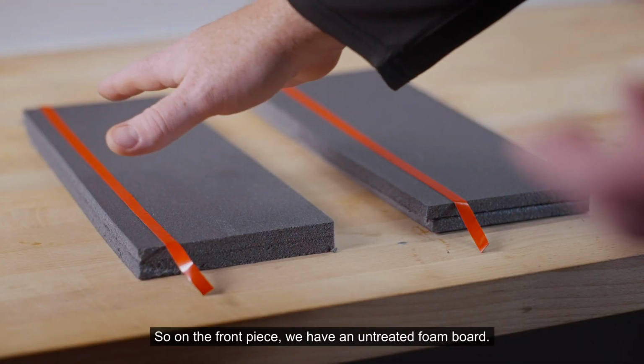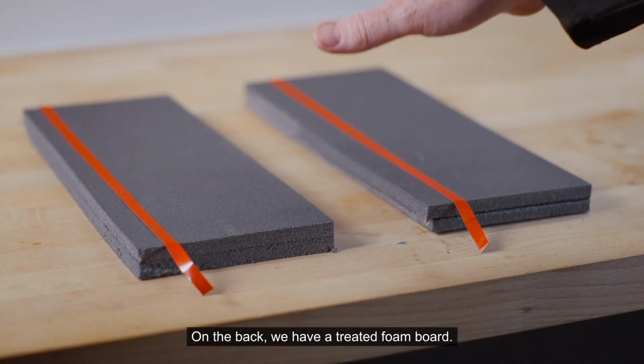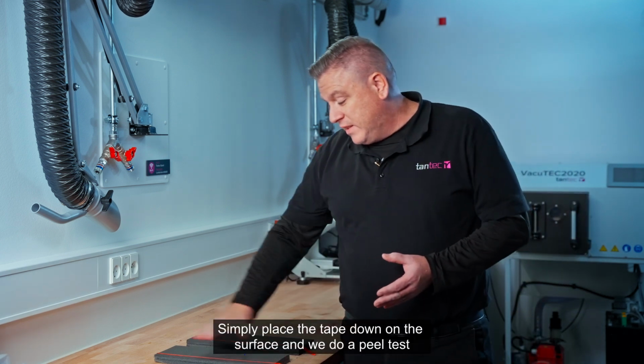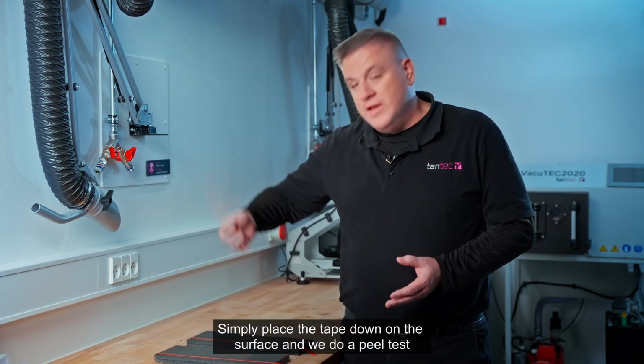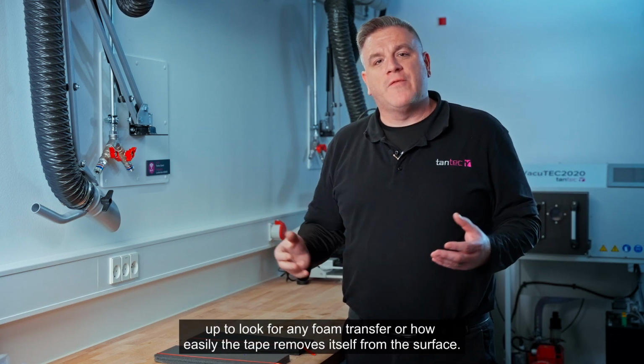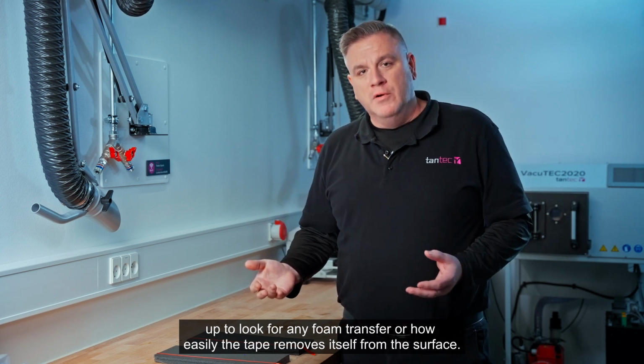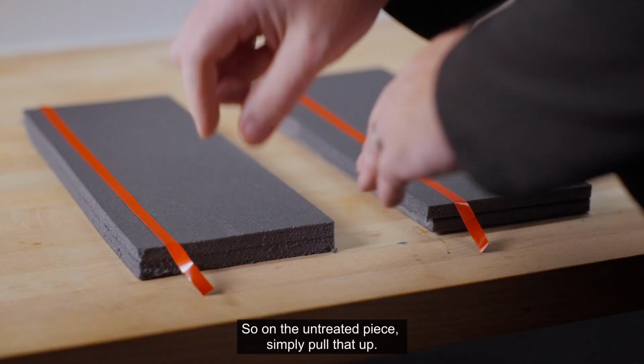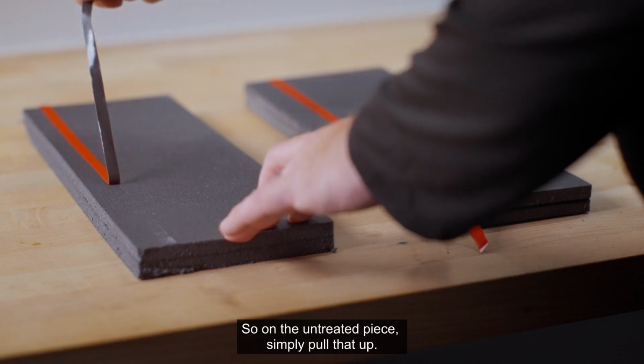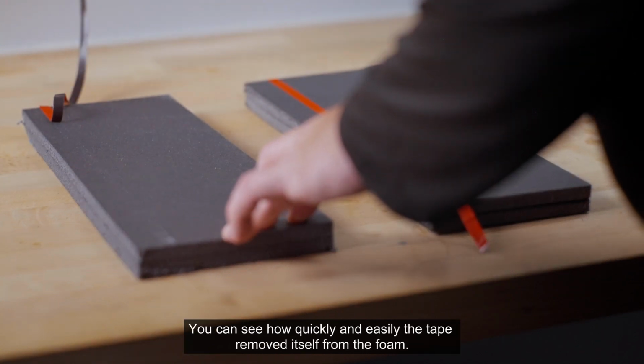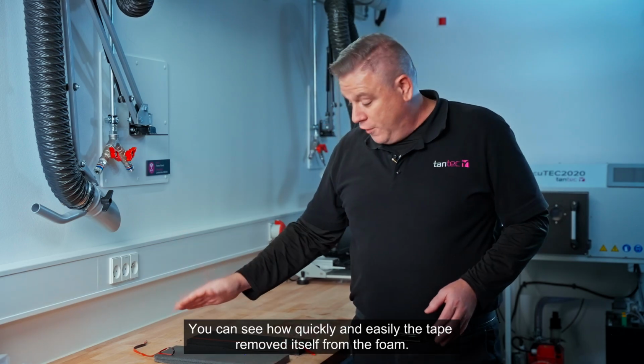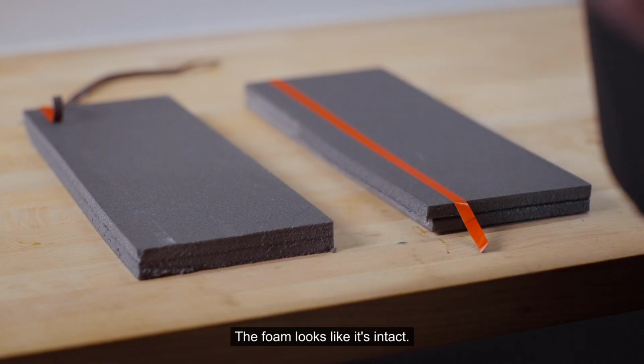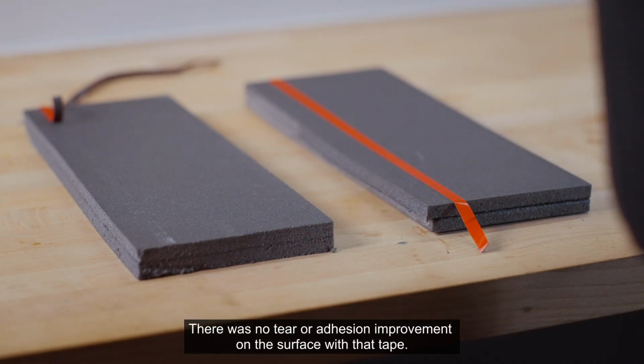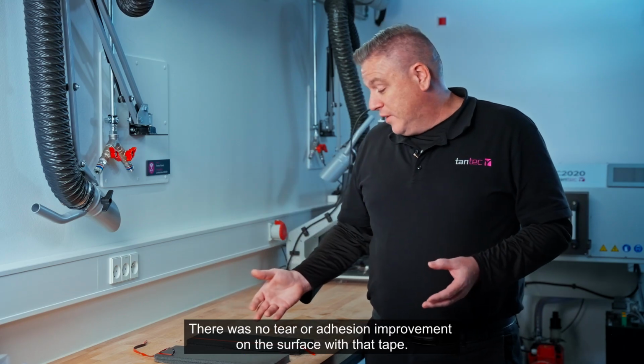So on the front piece, we have an untreated foam board. On the back, we have a treated foam board. Simply place the tape down on the surface and we do a peel test up to look for any foam transfer or how easily the tape removes itself from the surface. So on the untreated piece, simply pull that up and you can see how quickly and easily the tape removed itself from the foam. The foam looks like it's intact. There was no tear or adhesion improvement on the surface with that tape.